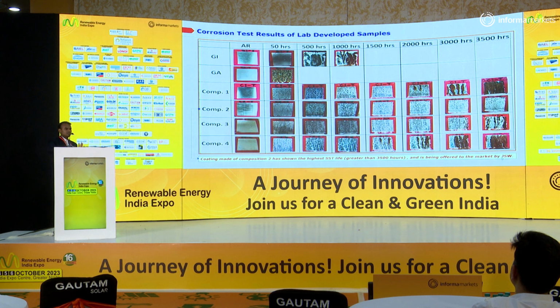These are the samples that we produce in the lab scale. So composition 2, which JSW is offering to the market currently, has shown SST, which was performed as per ASTM B117, has shown SST life of more than 3,500 hours. Compared to GI, which you can see in the first row, it is almost more than 5 times.